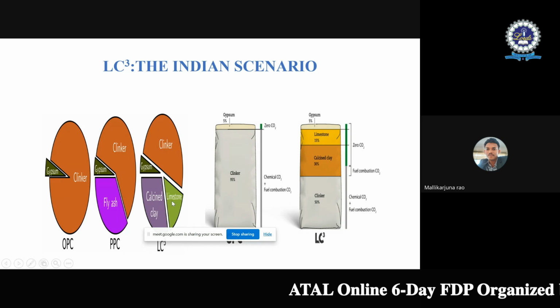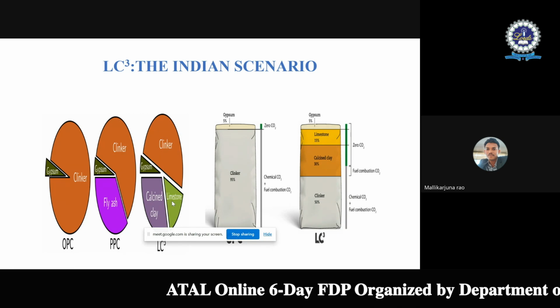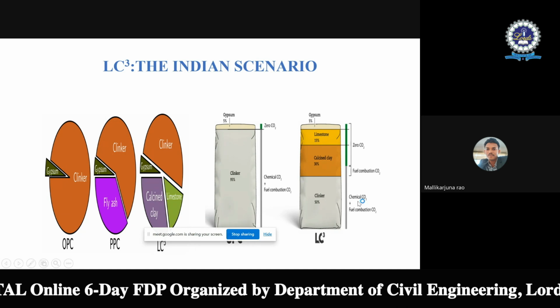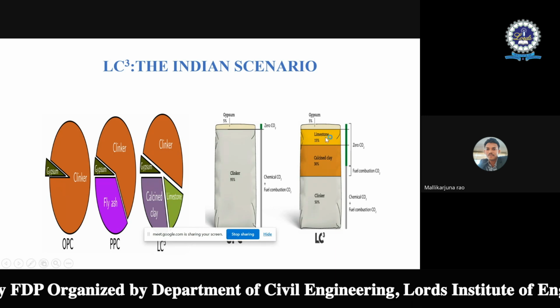See, in OPC you have a large percentage of clinker and a small amount of gypsum. In PPC, you have fly ash, clinker, as well as gypsum. But in LC3, the difference is that you have calcined clay, clinker, gypsum along with limestone. These four ingredients together are your LC3. For example, in LC3 you have 50% clinker, with CO2 plus fuel combustion, 30% calcined clay, 15% lime, and 5% gypsum.